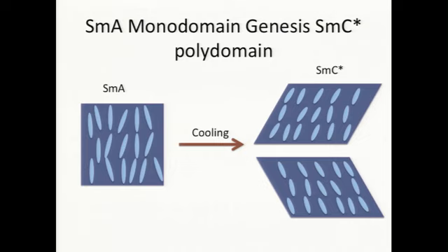Okay, so if you have a smectic case, you know that smectic liquid crystals are layered. And if it's smectic A, it all points like this. And then if you have it in the solid and you cool from smectic A to smectic C, then the rods tilt relative to the layer normal, and that's accompanied by a shear. That's the mechanical consequence in the elastomer context. And this shear could happen in either direction, or indeed, honestly, it could happen on a cone. So this is a different continuous symmetry that's been broken, and therefore there's a soft mode associated with that shear angle.